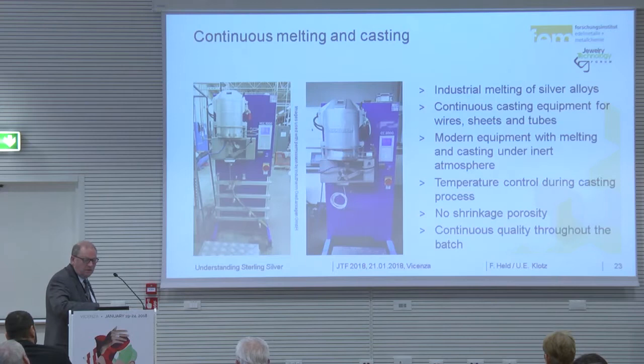Processing of silver alloys at this time mostly uses continuous melting casting equipment. With it you can make atmosphere controlled, you can make vacuum, gas, argon, whatever you want. With the continuous casting, you have temperature control during casting. You have no shrinkage porosity, continuous quality through the whole batch.